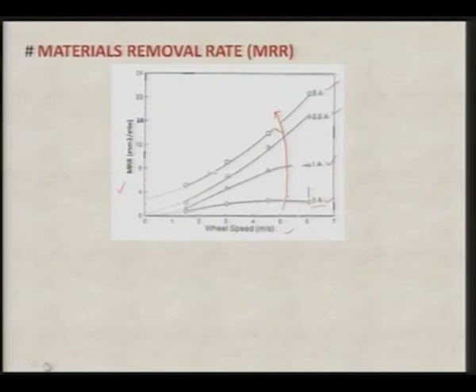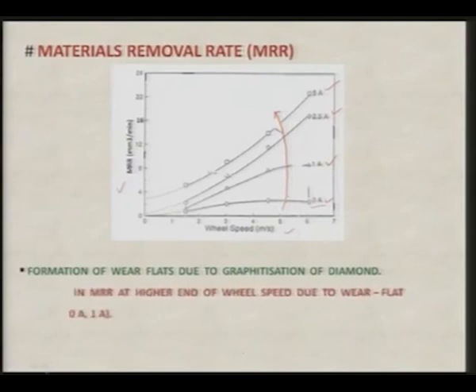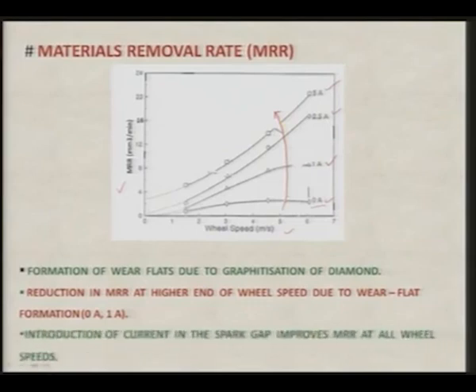Now, apart from that, formation of wear flats due to the graphitization of diamond takes place, and then you have reduction in material removal rate at the higher end of wheel speed due to the wear flat formation, as you can see here. Introduction of current in the spark gap improves material removal rate at all wheel speeds. Another point is, as the wheel speed is increasing, the material removal rate is also increasing. So, with the increase in the current or the wheel speed, material removal rate is increasing continuously, and this is the minimum wheel speed that we use while performing the experiment. So, we have extrapolated this to the material removal rate axis, and you can see that even with the 0 current you are able to get certain material removal rate.